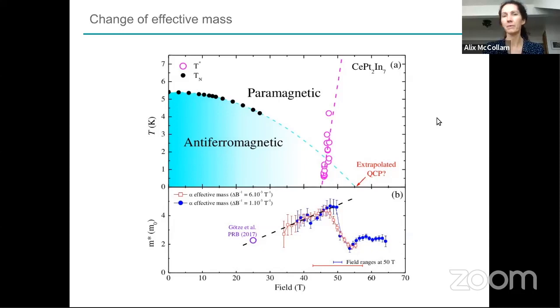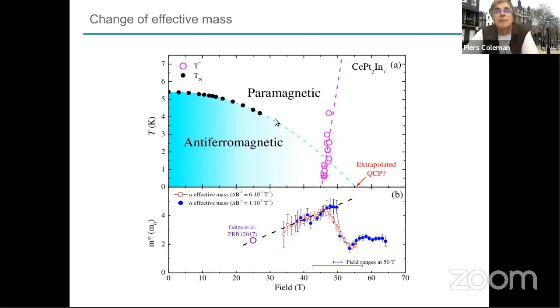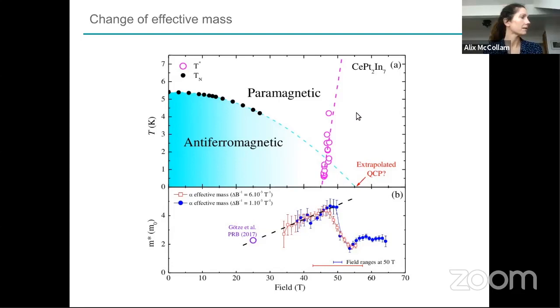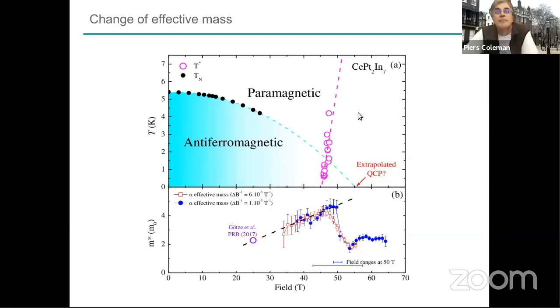So the gamma is comparable to the 115s, and also the condensation into the superconducting state. It's the heavy quasiparticles that are going in. So the superconductivity under pressure is very comparable to cerium rhodium indium 5. So the numbers are quite similar. I think the heat capacity, gamma, is a little bit lower, but it's of the same type of number. I don't have the exact.